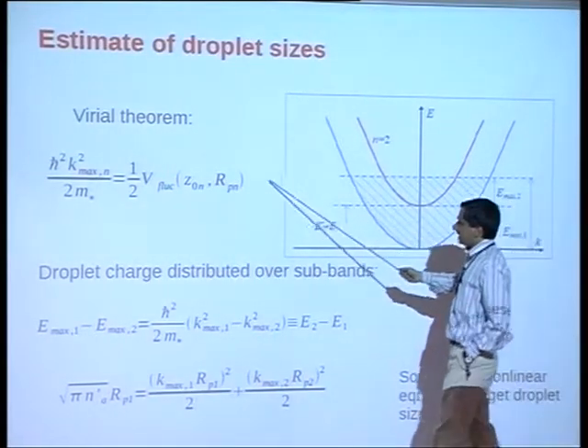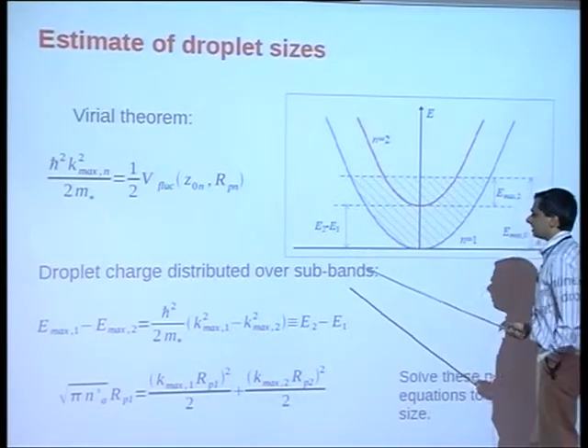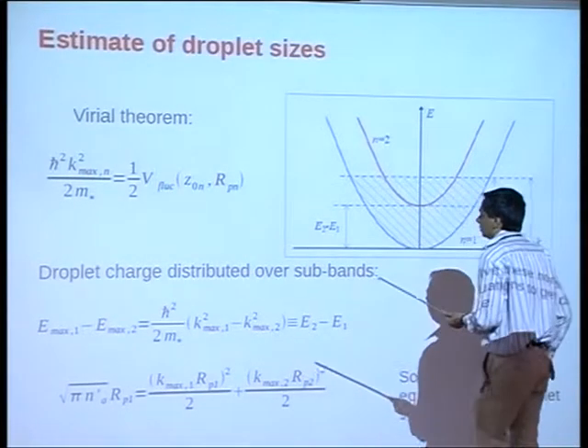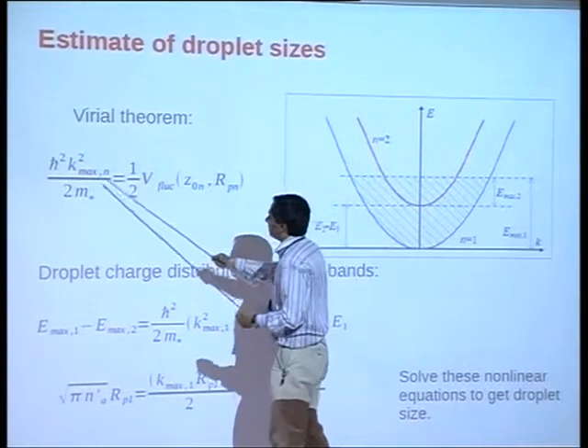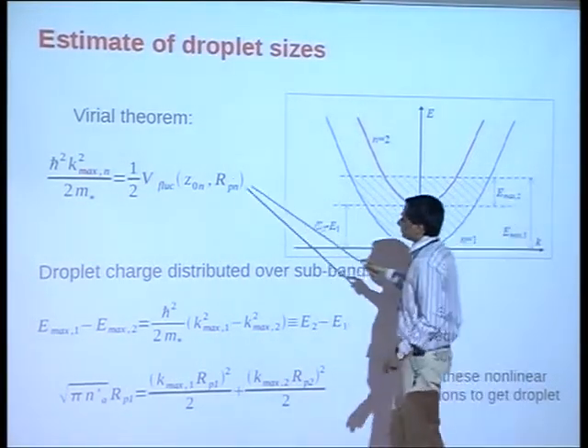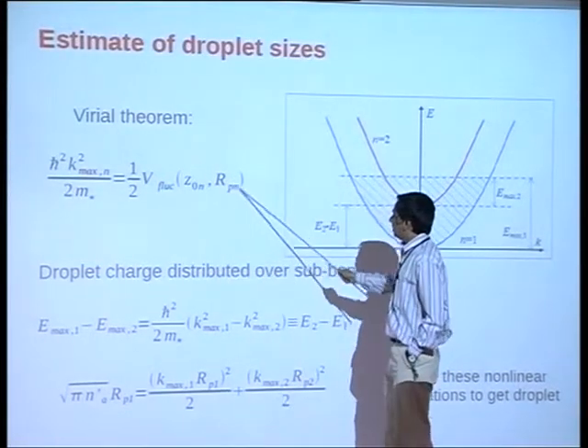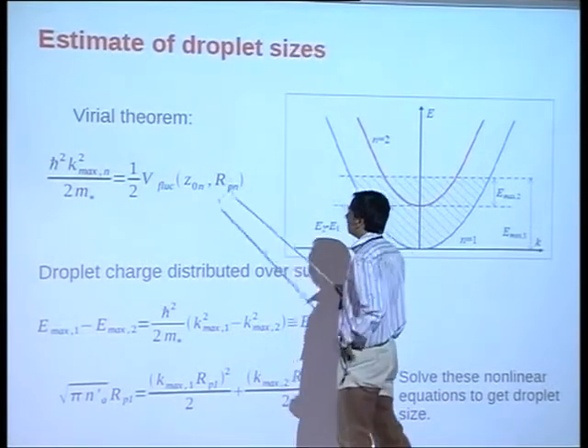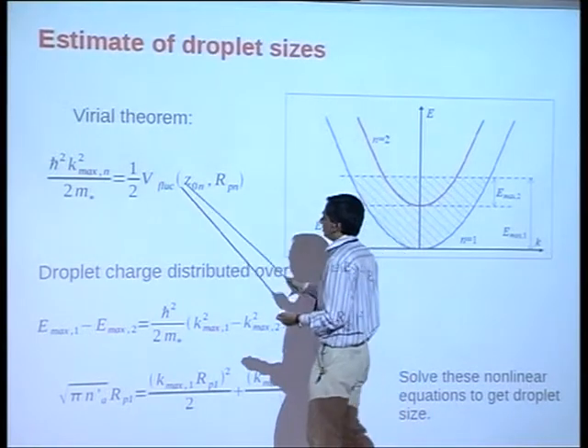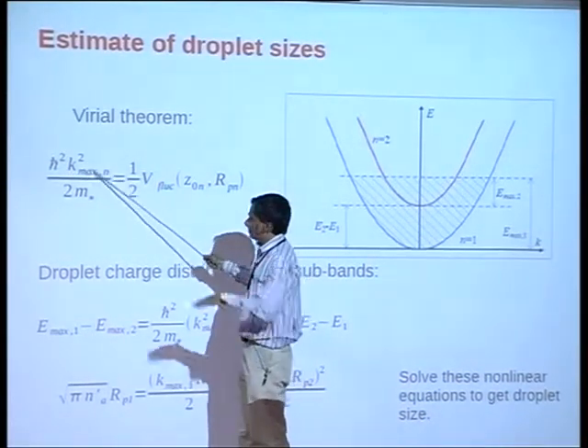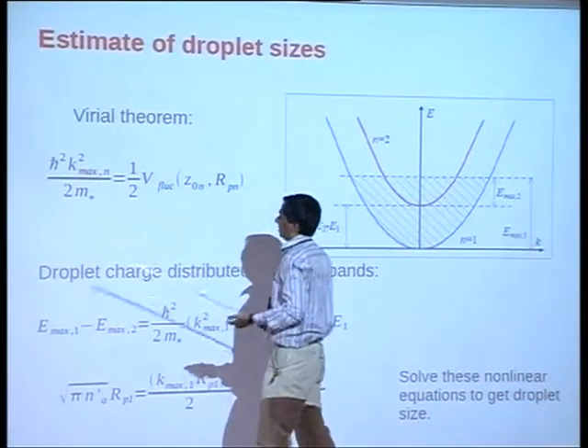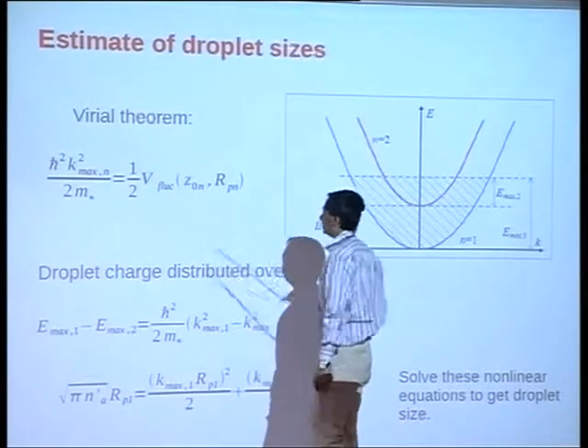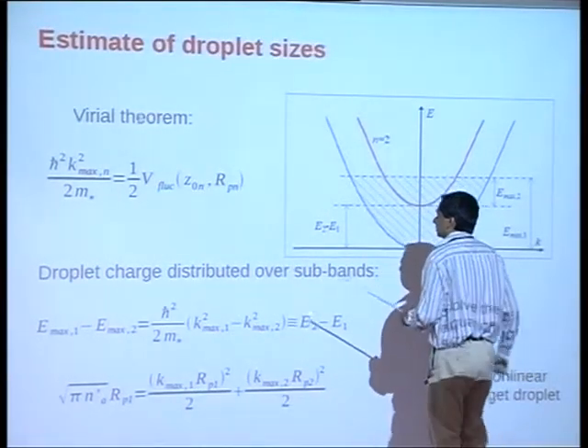One can actually follow a very clever set of arguments to estimate the size of these charge puddles without doing much numerics, in fact any numerics. The rough idea, which goes back to Gergel and Suris and later to Shklovskii and Efros, goes like this. Suppose I look at the potential fluctuations on a length scale R puddle, which is the length scale of the puddle size. It will have some fluctuation potential which has created a well. I start populating it with holes and fill it up to some maximum level, which I label by K max. This is very simple-minded, some wave vector of transverse quantization. And the virial theorem allows me to form such a relationship between the two. And this is like estimating the energy from the bottom of the potential fluctuation.